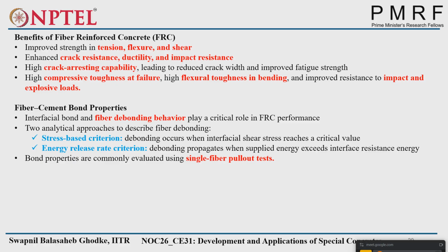We have a certain amount of interface resistance energy and a certain amount of tensile stress energy. So based on that, energy release criteria have been developed. Bond properties are commonly evaluated using the single fiber pull-out test. Similarly, for the bond pull-out test, we do it for rebars for a single bar only. Here also, the single fiber pull-out test will be done.